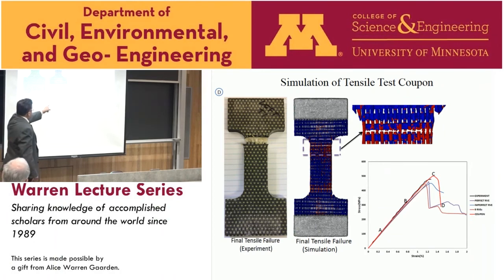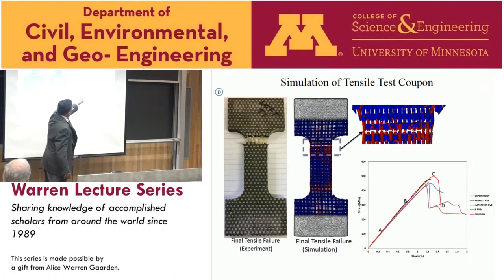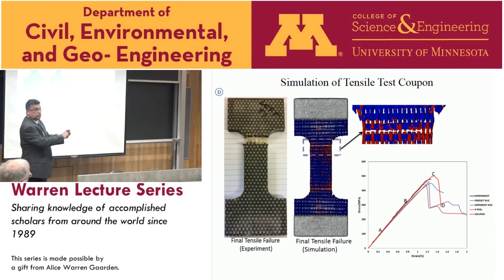Now, what I'm showing here are what we actually see in tension. This coupon fails like that, and that's that black curve there. And then after that, the load drops, right? So we did RVE studies. We took representative volume elements, and we did a perfect RVE, an imperfect RVE that was scanned and constructed more accurately.